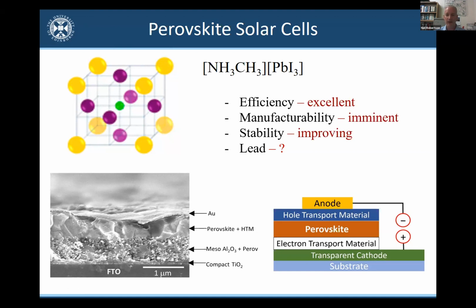It has been pointed out that the amount of lead in a lead halide perovskite solar cell is less than you get in a crystalline silicon solar cell in the solder. So actually the quantity of lead is absolutely tiny, because these are thin film absorbers, really nanometers thick in order to form the active layer. The disadvantage being, of course, that this is soluble lead, unlike lead used in solder, so it may be more bioavailable. So that's why there's still some debate around the extent to which toxic lead might be a problem.